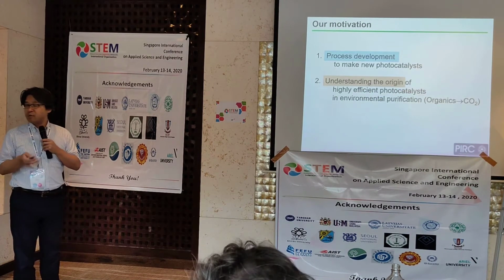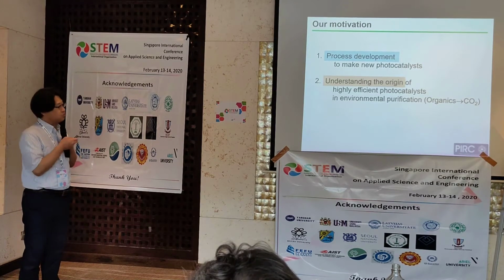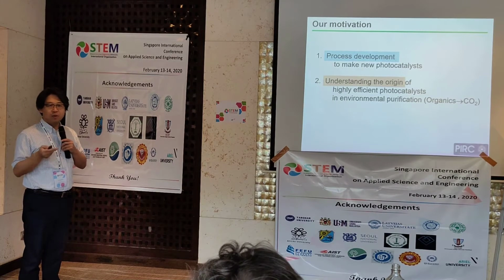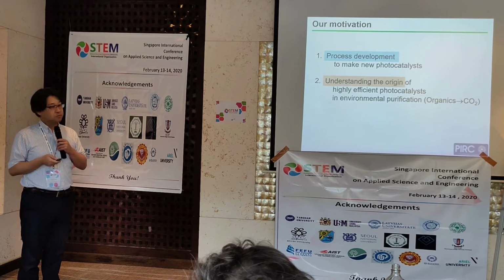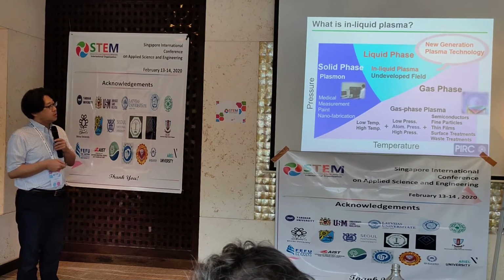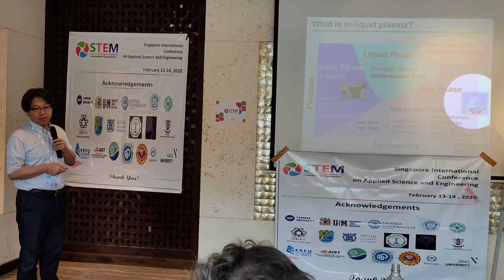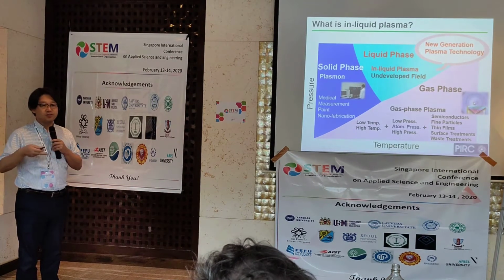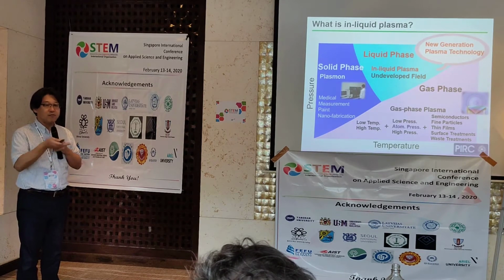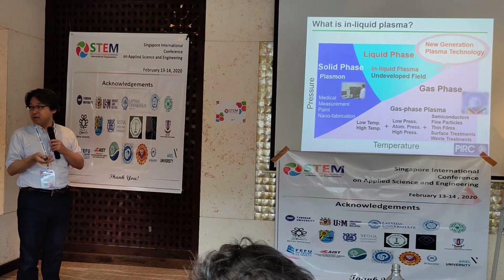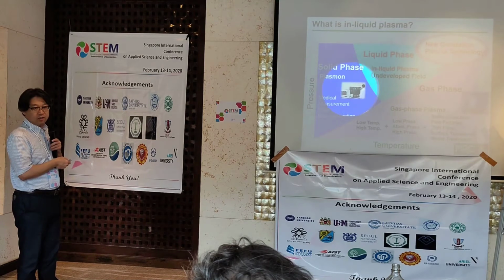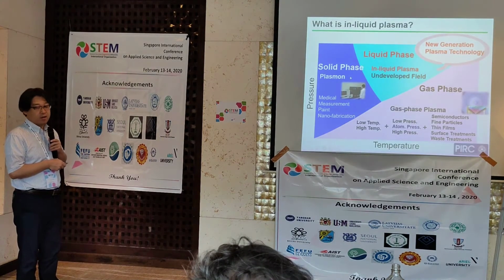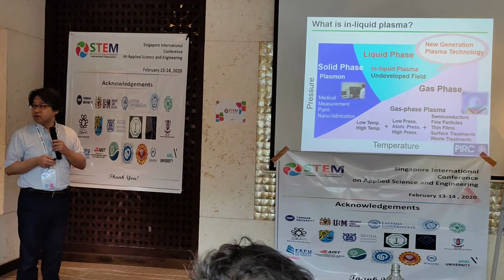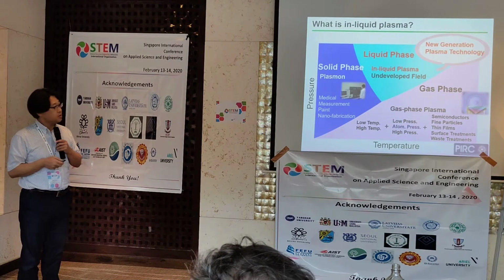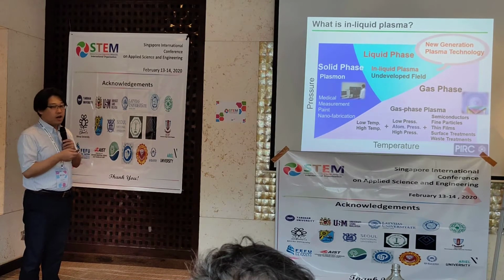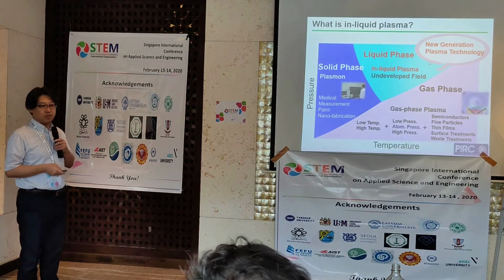So today I report about a new, very unique process to make this material, and second, how this new material works to activate the photocatalytic reaction. Plasma in the gaseous phase is well known and already utilized in semiconductor manufacturing to make thin films using sputtering and CVD. In the case of solid phase, this is also named a plasma phenomenon. But how about plasma in liquid? This is a very new generation plasma technology, an undeveloped field. Today I introduce in-liquid plasma treatment of titanium dioxide.